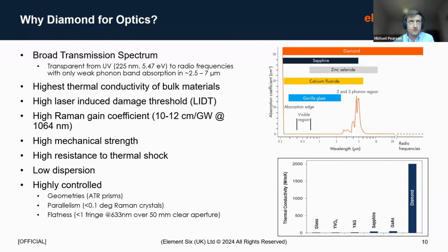Well, if we think about, for example, optical coatings, if we took a piece of zinc selenide, which is typically used at the 10.6 micron CO2 laser wavelength, and we compare that to diamond, which is also often used at 10.6 microns, both of those materials will need an optical coating in order to get the high transmission values that you require for your application. In the case of zinc selenide, if we have small amounts of absorption in the optical coating, the very low thermal conductivity of the zinc selenide means that heat takes a long time to get out of the coating, and it leads to high peak temperatures in your optical coating, which can lead to premature failure.